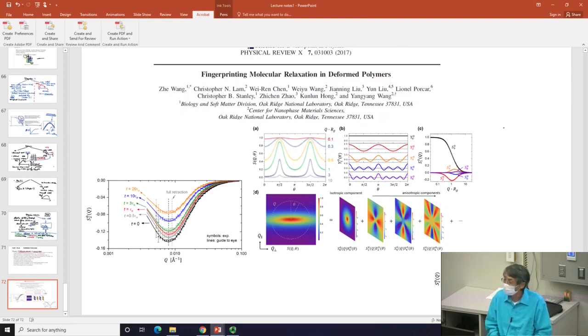In particular, he recognized that one way of analyzing neutron scattering data was to do it as the people who have done it for colloids, which is to treat the raw data directly, looking at the intensity and breaking down the neutron scattering intensity directly in terms of summations of so-called spherical harmonic functions, so that your analysis will not be model dependent per se.